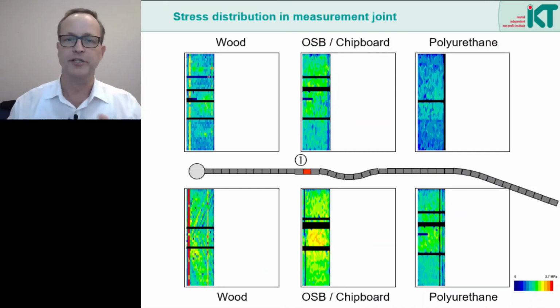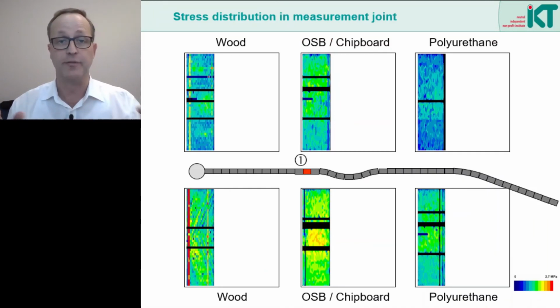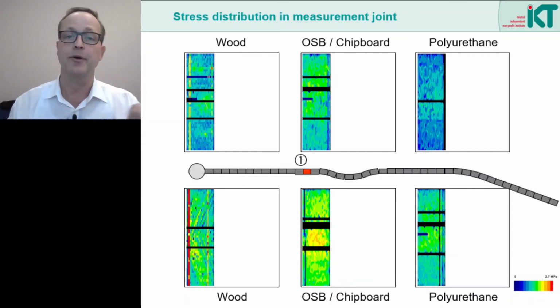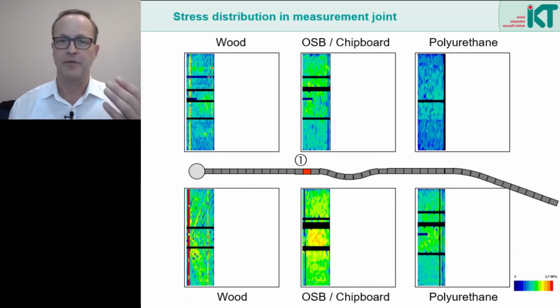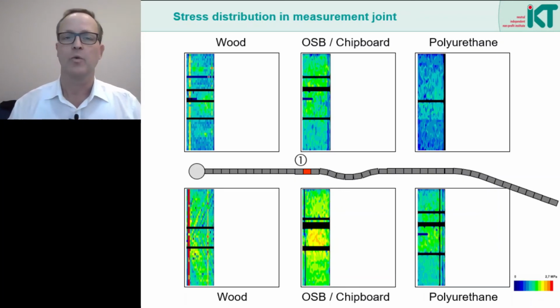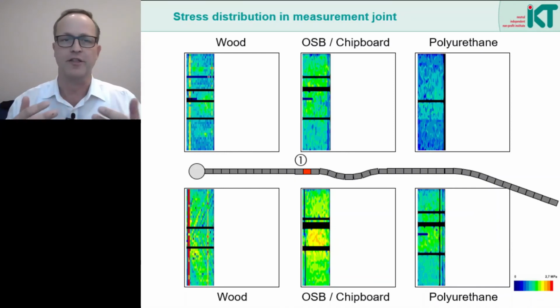Here we see the pressure distribution in the left and right extreme of the spring line, first a solid wood, then a chipboard and a polyurethane ring. The measuring joint has been pushed forward to point 1, which means that the first straight line has almost been completed. We see quite similar results for all pipe joints. The stresses are in the low or medium range and they are distributed quite regularly. Don't bother about the black bars, they are only failures of the measuring sensor.